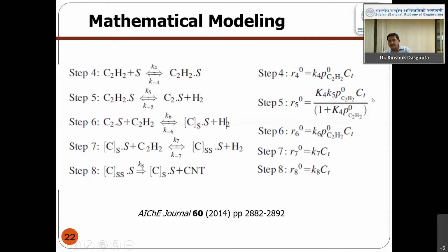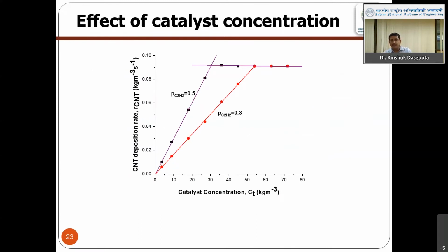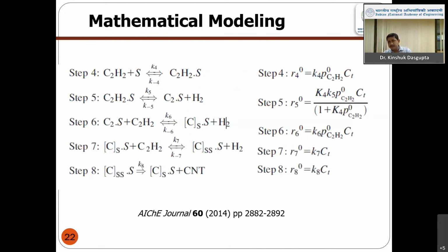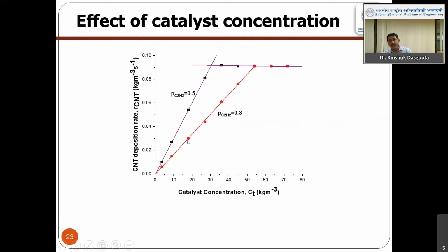So this is the final form of the equation if we consider each step individually as the rate controlling step. Our aim is to see, if we look at these equations, CT means catalyst concentration. So for all the equations, the rate varies linearly with catalyst concentration. So let us check. We varied the catalyst concentration at two different partial pressures of hydrocarbon, and we could see whether there is a linear variation with respect to the rate of carbon nanotube deposition.